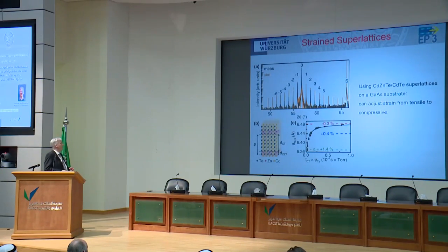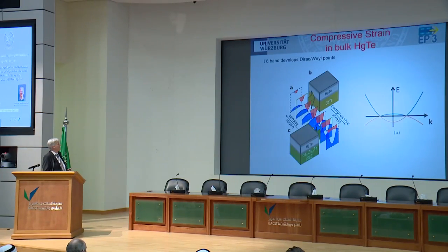But we are able to actually accommodate all the strain between the superlattice and the gallium arsenide substrate in the first layers of cadmium telluride. And then by varying the periodicity of this superlattice, we can now tune the strain that we have in our epi layer from the tensile strain I already showed you to a very strong compressive strain. Now, why are we interested in compressive strain? Well, basically, if you go to compressive strain, you now do the opposite of what we did with the tensile strain. With the tensile strain, we pulled the gamma 8 bands apart, the light and the heavy hole. And with the compressive strain, you pull them through each other.